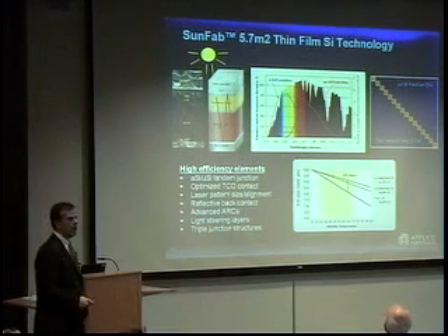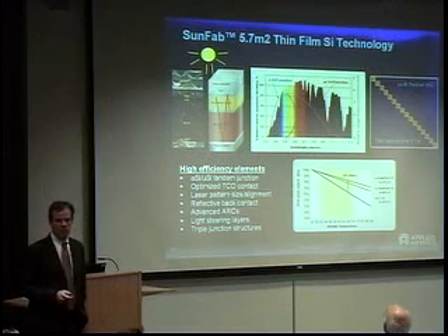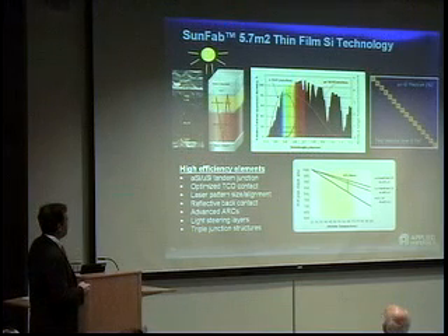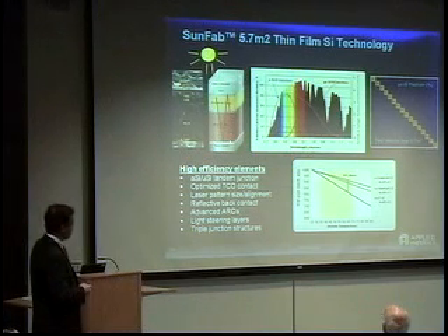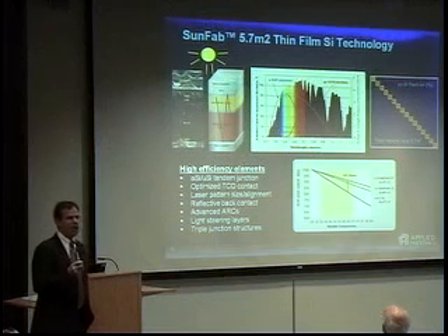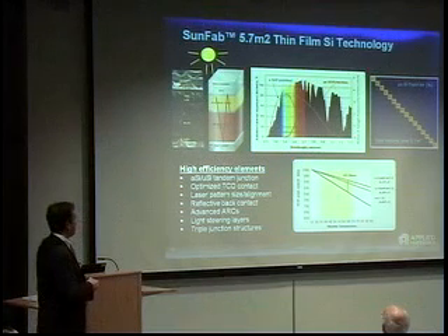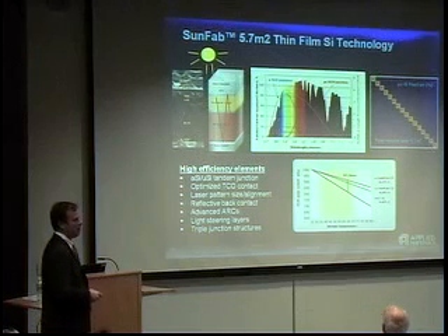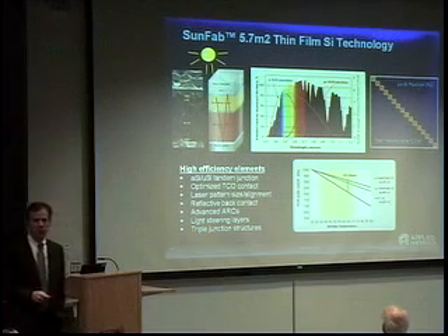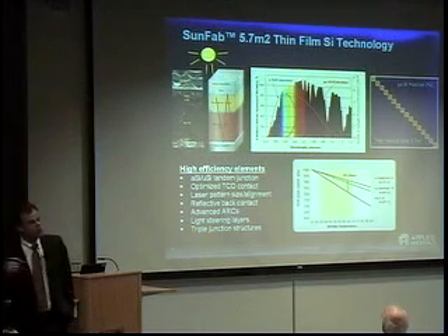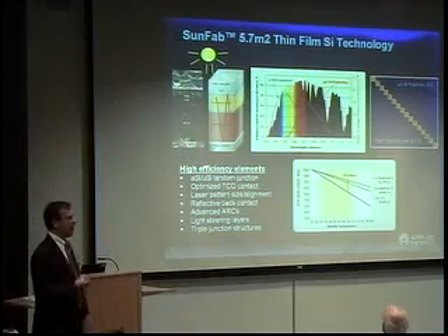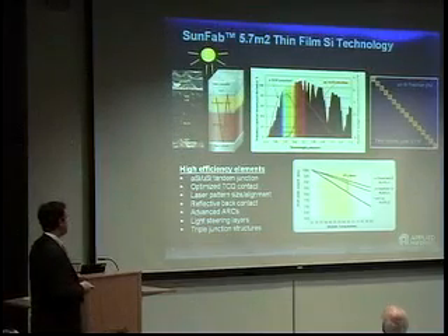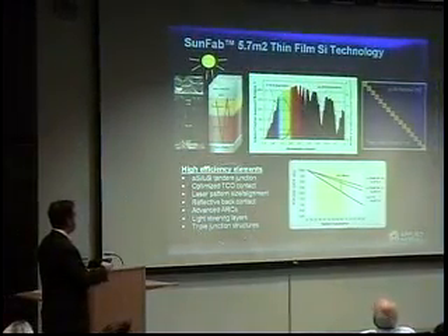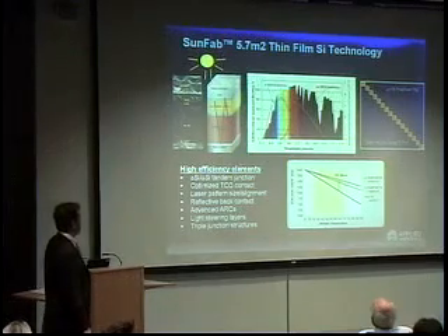The trick of all of this comes down to uniformity. Not only do the layers have to be uniform, but the band gap has to be uniform. So the band gap of the microcrystalline silicon has to be the same from one corner of that 5.7 square meter substrate to the other, and we've got to have substrates going in there at 20 per hour. That's a real challenge. A lot of things we can do to make this device more efficient.